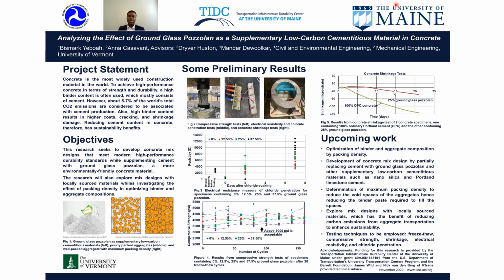Figure 4 shows the results from compressive strength test of specimens containing 0%, 12.5%, 25%, and 37.5% ground glass pozzolan after 20 freeze-thaw cycles. The specimen containing 0% ground glass pozzolan attained the highest compressive strength of about 5,000 psi, followed by the specimen containing 12.5% ground glass pozzolan. And it can be seen here that the greater the quantity of ground glass pozzolan, the more the compressive strength is reduced. But these values are all above 3,000 psi, which is acceptable.